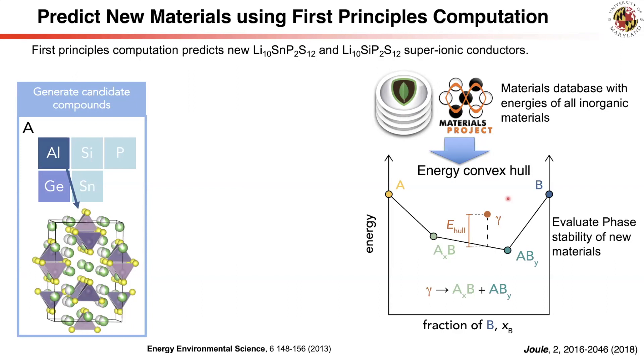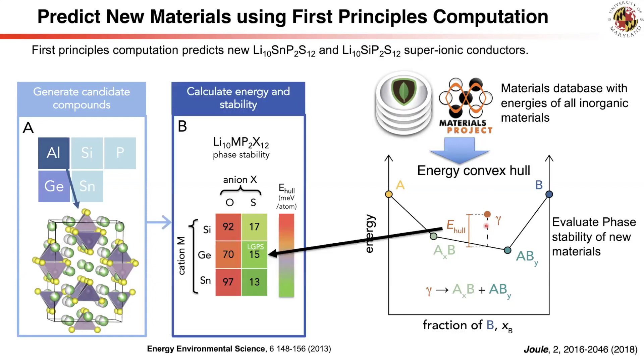By comparing the energy of the predicted material with its competing phase equilibria, we obtain the energy above hull, which is the descriptor of phase stability. A higher value indicates a more favorable decomposition reaction, meaning a less stable material. The original LGPS has a reasonably low energy above hull of 15 meV per atom. The predicted materials substituting germanium with silicon or tin have a similar energy above hull, suggesting they are likely synthesizable in the lab.